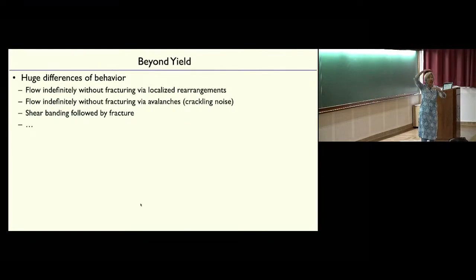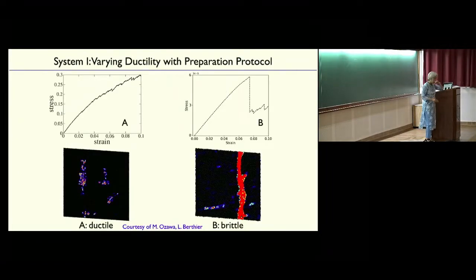If you shear like this, you have a linear velocity profile. That's what you get for foams and for ductile systems. But instead of that, what you can get is the strain all gets localized in a thin layer. That's the shear band. And then you can get fracture. And some others, they don't even shear band, they just fracture right away. So you see very, very different behavior if you push beyond yield. And so what we want to do is use softness to get insight into what's different.